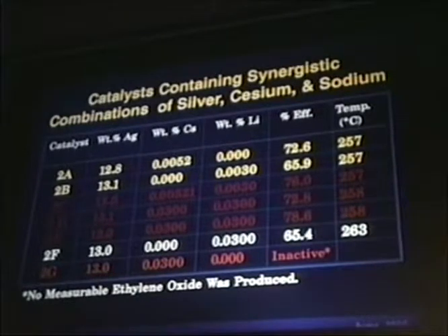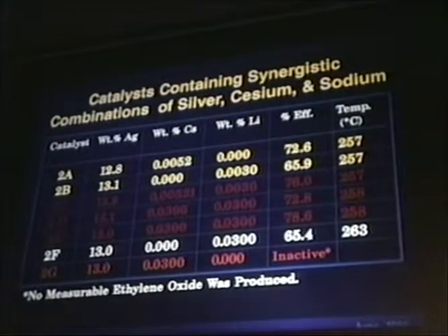The bottom catalyst, 2G, containing 0.0300% cesium and no other promoter, is totally inactive. The optimum amount for this system is 0.01 to 0.015%. So when you go to twice the concentration, it is totally inactive. However, consider the addition of 0.03% lithium. Lithium by itself is the next one in white, 2F. It's very inefficient, in fact, no more efficient than silver by itself. But when you add 0.03 weight percent, and that is a lot of atom concentration, I'm sure you recognize, the efficiency is as high as some of the best of the mixed alkali promoter systems, 78.6%.